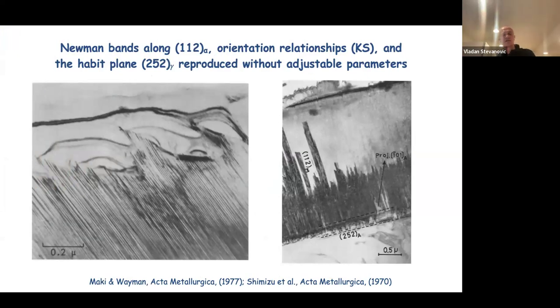So basically austenite has transformed into martensite. In the left picture, you find these lines, which are called Newman bands, which are twin boundaries. Slipping and twinning are related processes, because in our mechanism shown on the previous slide you could choose to transform one of these slabs by a mirror plane onto itself. Then in the final structure it will actually produce a twin boundary.